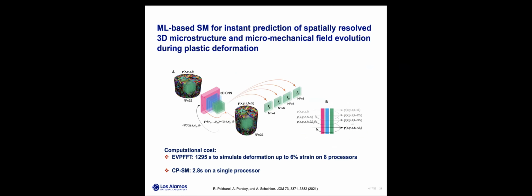Similarly, this surrogate model was then extended to predict not only crystal reorientation, but also micromechanical fields, and at multiple strain steps. So in this case, we decided to use a 3D convolutional neural network architecture with recursive inputs and outputs to predict both microstructure and micromechanical fields evolution. And again, we used EVP-FFT simulations for our training.